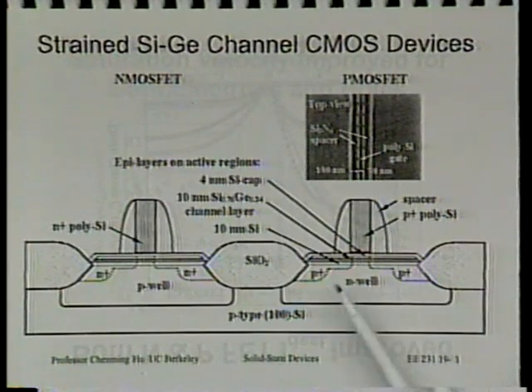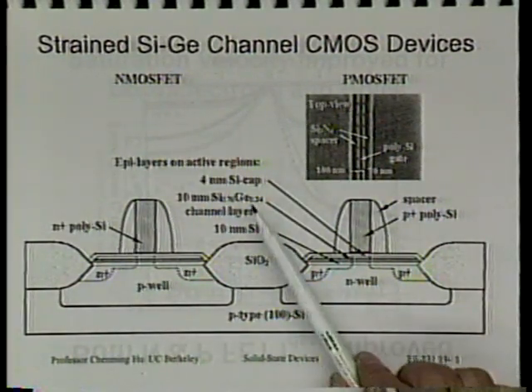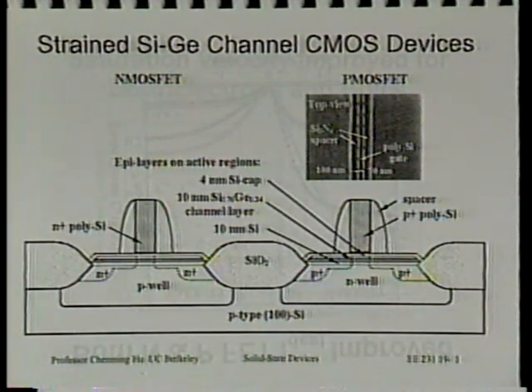Now, on top of the silicon germanium film, we grew a 40 angstrom silicon cap. We actually don't want that. The only reason we want a silicon cap is because we know we cannot grow high-quality SiO2 on silicon germanium. That's a known fact. That is one problem with using silicon germanium, okay? And that certainly still requires a lot of additional work. So the way we did it is to put on a very thin layer of silicon. We wouldn't have minded using even thinner silicon. And then oxide can be grown on top of that. Do you see the idea?